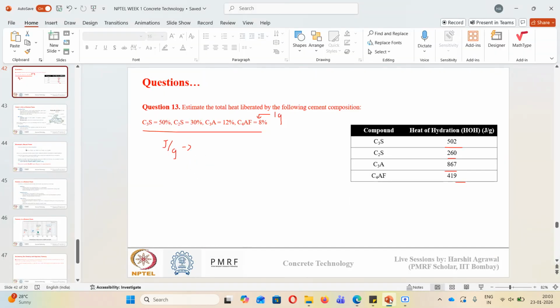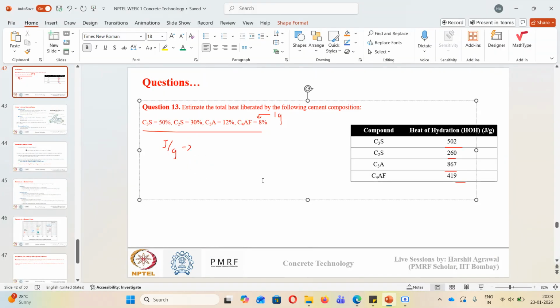Did anyone do the calculation? So the total heat of hydration will be 0.5 into 502 plus 0.3 into 260 plus 0.12 into 867 plus 0.08 times 419. So it will come out to be 466.56 joule per gram.